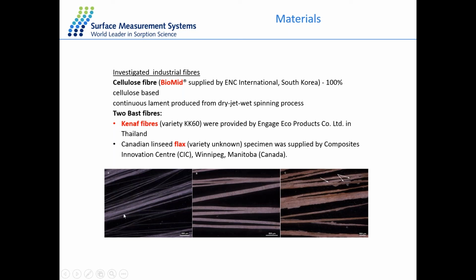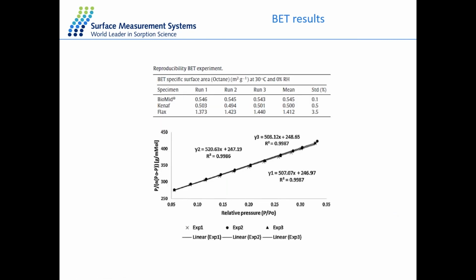And you can already see slight differences, especially in the cellulose fiber, which look quite uniform and thin fibers compared to the kenaf fiber and the flax fiber, which are showing some surface roughness on the material. So what we've done is calculated the BET surface area of the materials. So we've done a reproducibility experiment where we've done 3 consecutive runs and calculated the mean and standard deviation. So in this case, what we can see is that our flax fiber has a higher BET surface area compared to the other two. We can also see that the standard deviation varies slightly too, with the flax fiber having a higher standard deviation and our processed fiber having the smallest standard deviation.